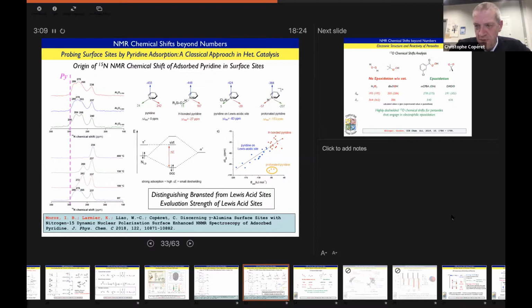So we have worked a lot with Guido Pintacuda. Typically, when you have a paramagnetic metal, it gets a bit more complicated because you have to be able to record the spectrum of the ligand. So in favorable cases, if you do copper 2, or we have done titanium 3 with Guido and other systems, you may be able to look at the anisotropy of the ligand. The problem is that in that case, your interpretation is complicated because now not only do you have a chemical shift anisotropy arising from the FMOs, but also the interaction of the electron with the adjacent nuclei. So you have a pseudo contact shift and a contact shift, and the information is there, but it's far more complicated.